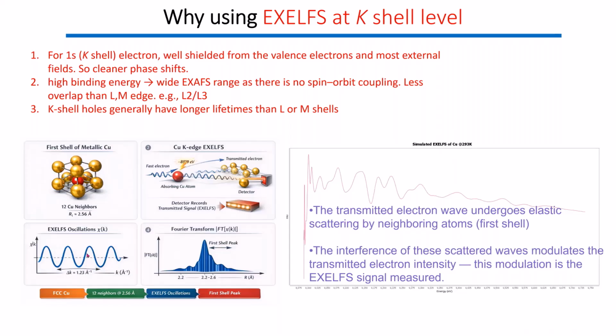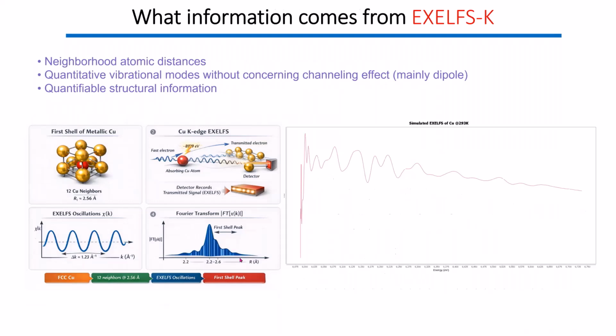And when we see these oscillations, as we mentioned before, if you take an FFT from there, you will see this so-called radial distribution function, and you can use that to analyze the neighborhood atoms and so on, the information. So what can we get out from there? Literally, because there is interference between neighborhood atoms, you can, of course, measure the atomic distance or the resulting lattice, or any lattice change between different shells as well.